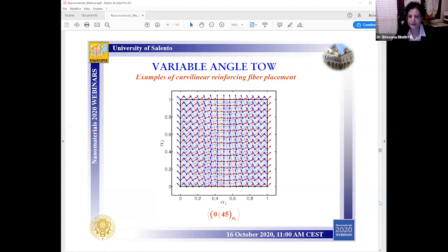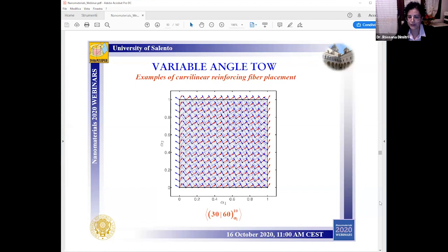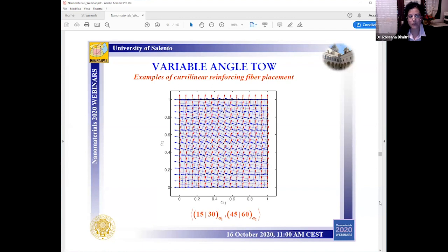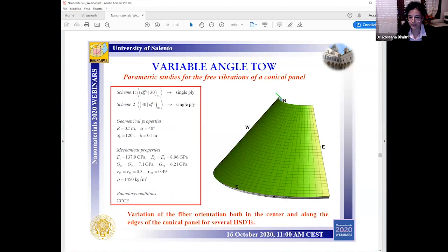And here are some examples of possible curvilinear paths of the reinforcing fibers as obtained with the previous law, by just changing the involved parameters. Now here I show you some results from a parametric study for the vibration response of a single ply conical panel, with the variation of the fiber orientation both in the center and along the boundary edges.